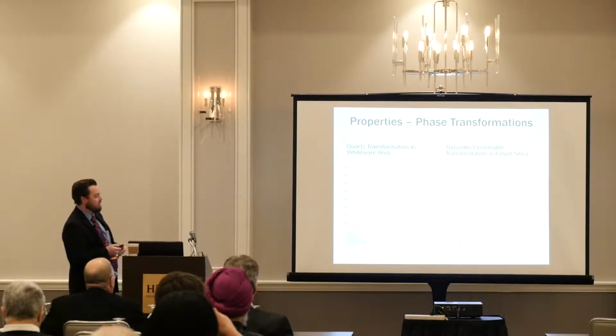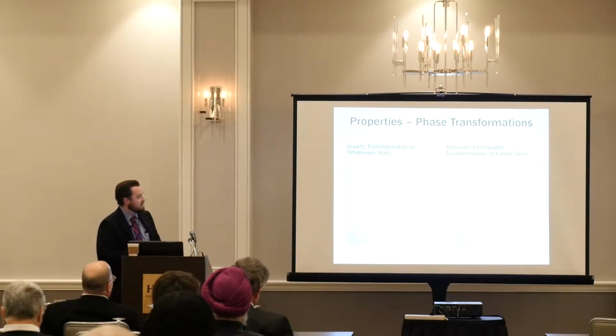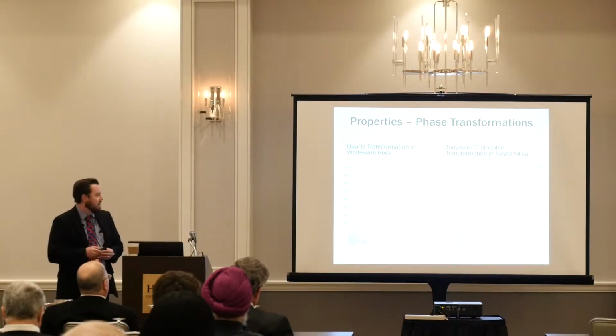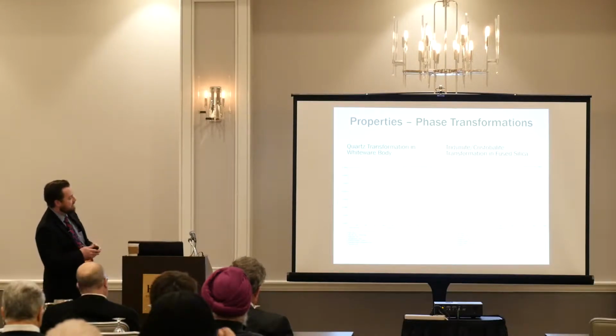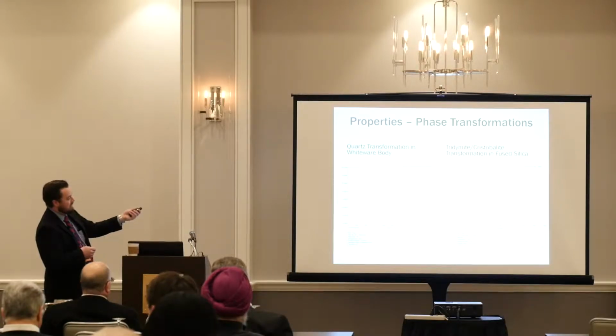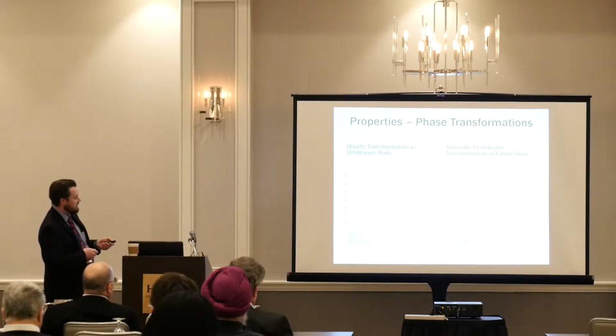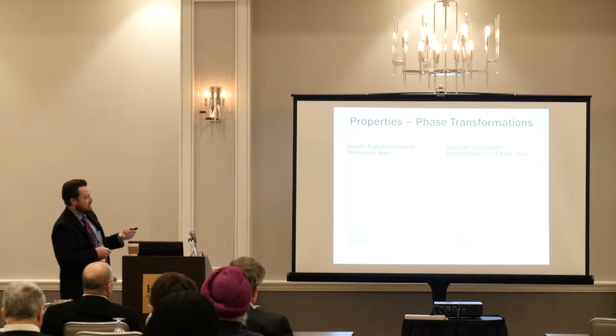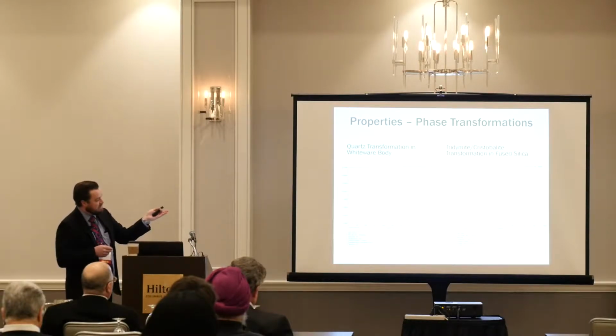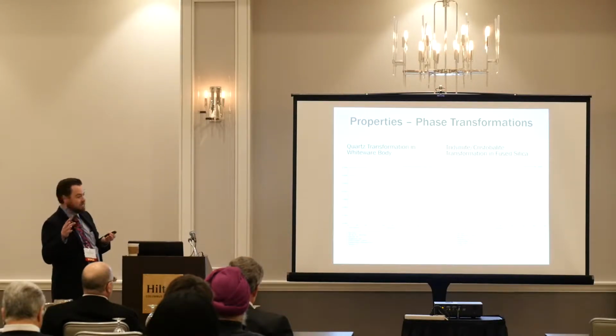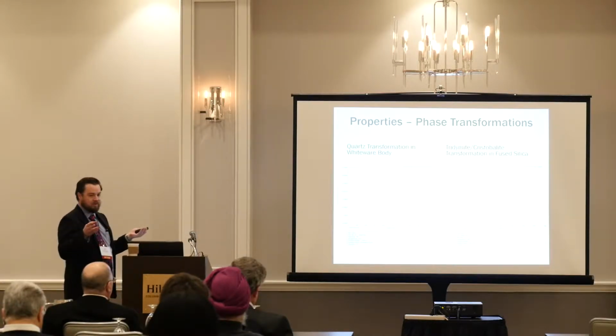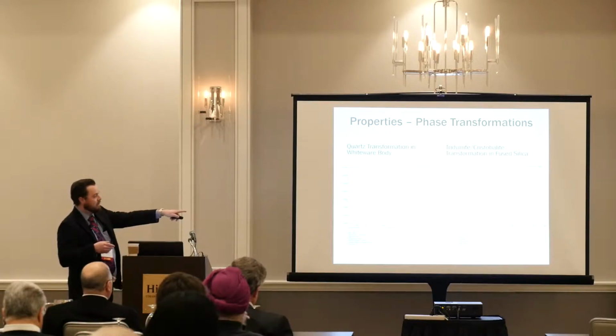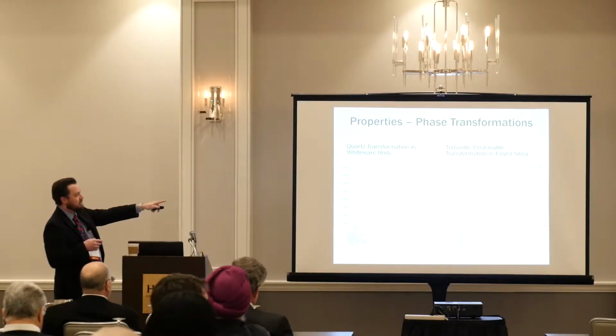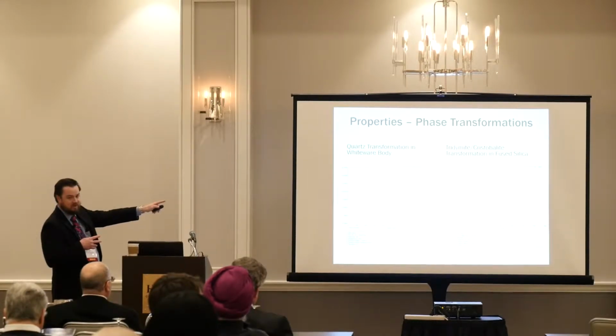What would that look like in those reports that we provide? Here on the left, you see that there's a quartz transformation in a whiteware body. Right there at 573, you see the shift on heating. And then on the right side, you can see another example from the slide I just showed you. On cooling, actually, it looks like it reached a high temperature and it allowed slight mobility, as you can see, kind of soften and bend over there. And then on the contraction, things are close enough to go ahead and react. And on your cooling, you're actually forming a combination of tridymite and cristobalite from the fused silica.